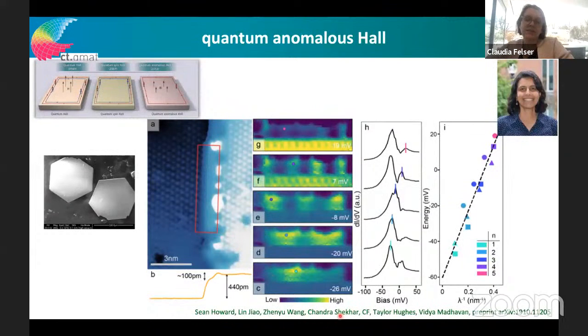And we have convinced some of our SDM partners here, Vidya's group, but also in collaboration with Heims, to look at our crystal, maybe at the edges. And indeed, if you go to the edges, you find a chiral current on a cobalt edge. And if you apply a bias voltage, you can really see nicely the quantization of the Hall plateaus in this material. So we think there is some evidence that we might find a quantum anomalous Hall effect here.